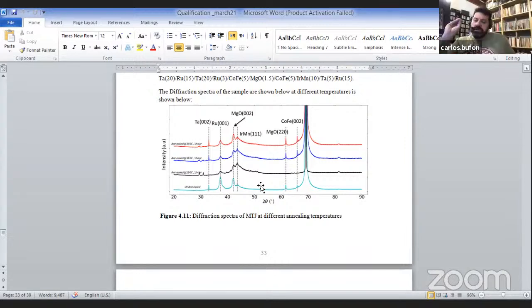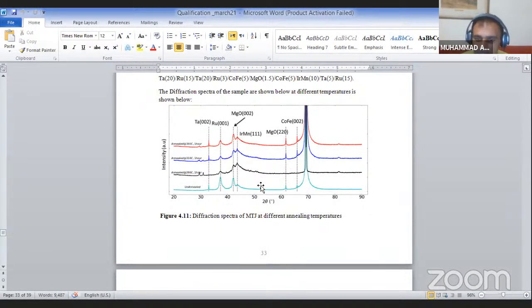So then you use oxygen just to prepare your aluminum oxide, correct? Yes, Professor. So in this particular case, how does your structure look? Do you have grain boundaries in your oxide or things like that? Professor, for the simple oxidation procedure, I introduce oxygen inside the chamber at a specific pressure like 25 millitorr. Then I shine my substrate with the oxygen plasma. We have a facility in the vacuum chamber where we can shine our substrate with the oxygen plasma as well. This oxygen plasma also oxidizes the layers we need.